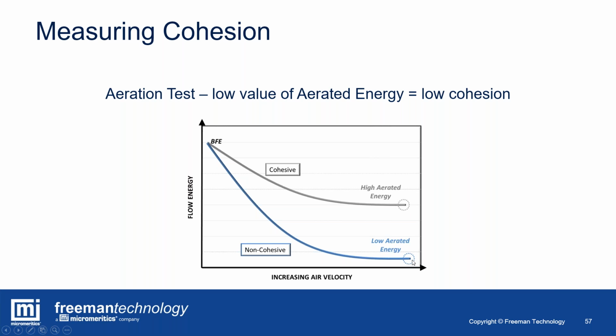Of course, for cohesive powders, you also get a reduction in flow energy, but you're not breaking down individual particle bonds. They may get separation between agglomerates, but those cohesive structures remain, and the change in flow properties is much less. It still becomes asymptotic. There's a steady state equilibrium, but basically what we're looking at here is a low value of aerated energy means it's a low cohesion system. It can become fluidized or aerated. A high value of aerated energy means you've got a significant amount of cohesion within the bed.